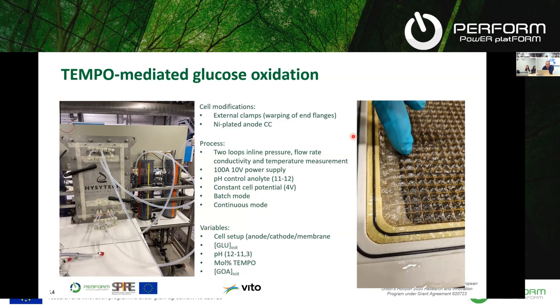And then we used this cell with two continuous loops, so anodic and cathodic loop. It was connected to a pilot installation with a 100A, 10V power supply, control of the pH of the anolyte, and constant cell potential was applied. At first, we were using a batch mode, so we started with a typical glucose concentration and just let the reaction evolve. But later on, we also used continuous addition of glucose to monitor the reaction.